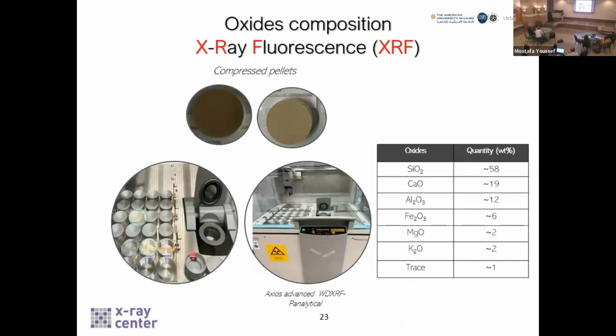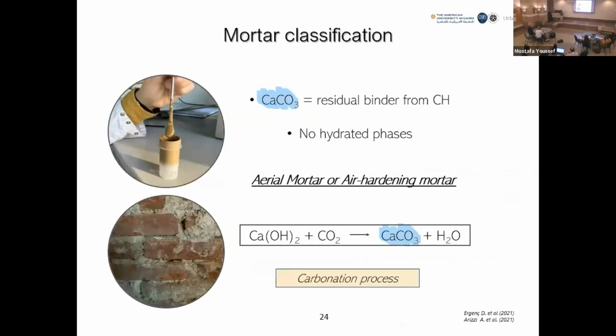And moreover, to go deeper with the chemical analysis, I also did some XRF in order to know the oxide composition of the sample. And as you can see here, the results that I was able to obtain are in line with the results related to XRD. And so, putting together all the chemical analysis that I did, plus some research in literature, I was able to classify in a better way the mortar that I'm working on.